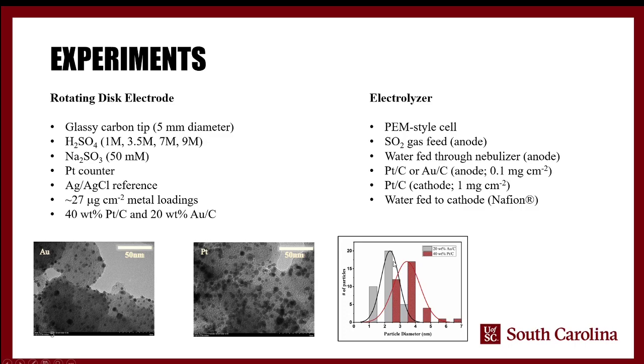So with the rotating disc electrode, we used a glassy carbon tip because it's both stable and inert for the sulfur dioxide reaction. We used 4 different concentrations of sulfuric acid, 1 molar, 3.5 molar, 7 molar, and 9 molar. And what those represent are effectively the startup and then approximately the steady state of what an electrolyzer would run under. And the reason we do that is we need to see how the concentration of the sulfuric acid actually affects the performance of the catalyst.